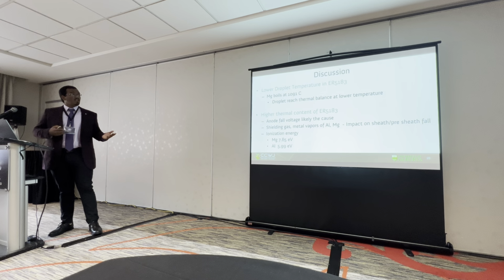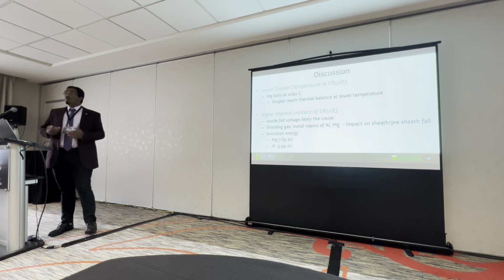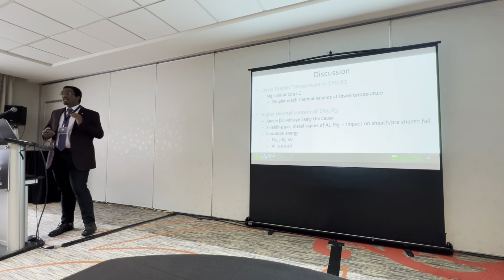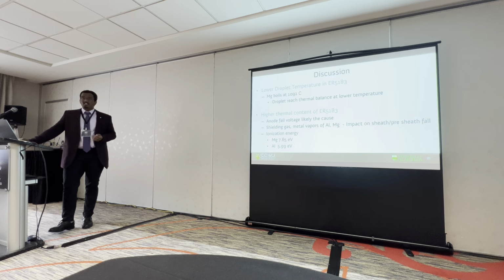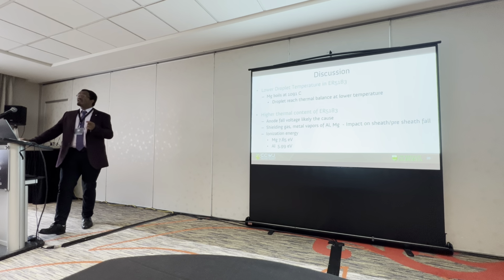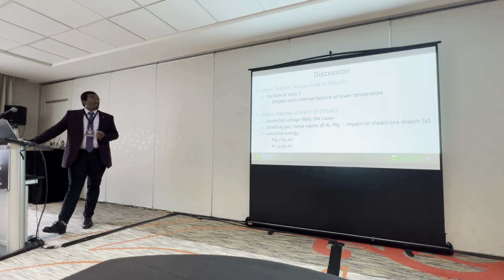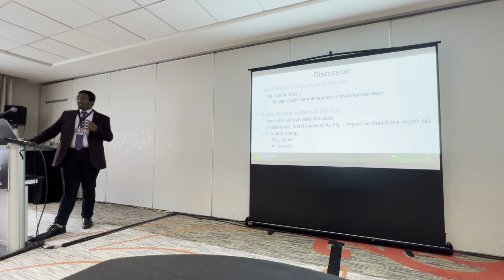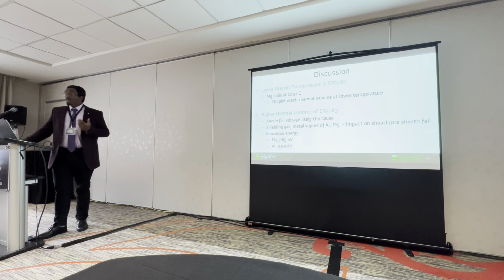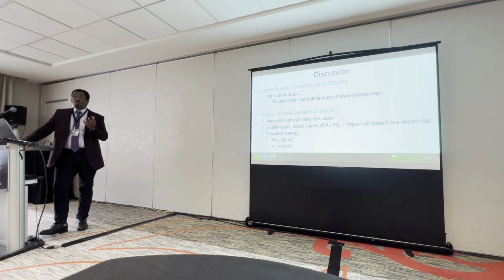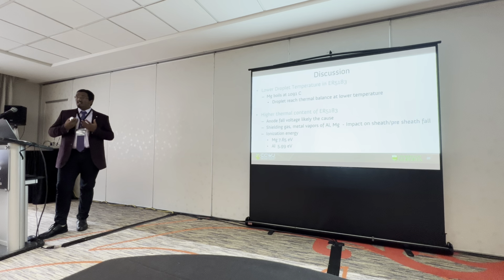So to discuss, the reason we have a lower droplet temperature in 5183 could be attributed to the fact that magnesium boils at 1091 degrees Celsius, which is really low compared to our high droplet temperatures. And this boiled magnesium could cause a local thermal balance around the droplet, forcing it to have a lower droplet temperature. And the higher thermal content of 5183.